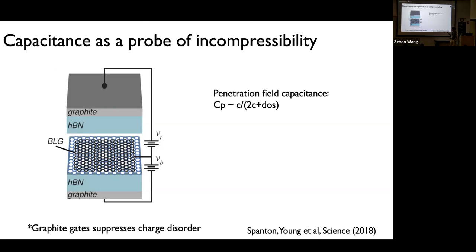Then you can immediately guess that it would depend a lot on the electronic properties of the bilayer graphene sample that you have there. To give you an example, if this layer is very compressible, like a metal, the electric field lines trying to go out will get screened out. So the signal that you get when you measure the voltage on the top graphite would be very small. On the other hand, if this sample is insulating or incompressible, then it almost behaves like nothing, or vacuum, so what you get is close to just two parallel capacitor plates, which is not screened. So by measuring this penetration field capacitance, you can easily tell whether the system is in a compressible or an incompressible state.